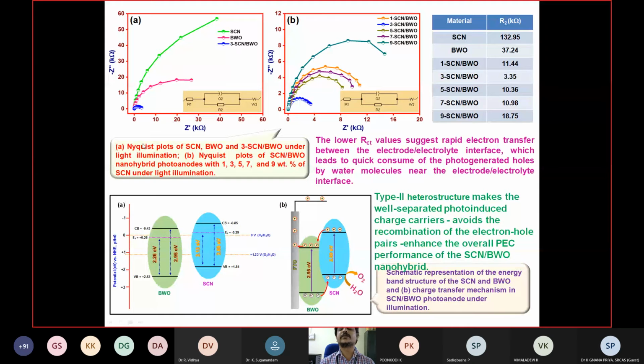Okay, then for the charge transfer dynamics, we calculated the RCT value using the electrochemical impedance method. Among the various materials, the sulfur-doped graphitic carbon nitride with 3 weight percentage showed a very low RCT value. That reveals this material suppresses the charge recombination process. Based on the values derived from the literature as well as the band positions, we proposed this mechanism. Here you can see the band positions for both semiconductors while they are separate. After making the heterojunction, this will oxidize the water and produce oxygen and protons. Then the electrons move through the circuit, and those electrons will reduce the protons to produce hydrogen. So this is why we proposed this.